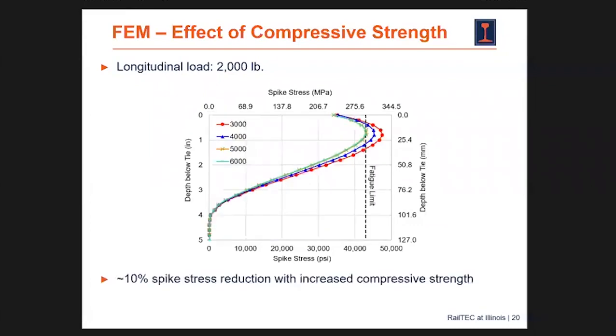Again, we're applying a 2,000-pound longitudinal load. And whenever we look at our values, originally we're above our fatigue limit. So we would expect failure to occur whenever we have only 3,000 pounds or 3,000 PSI material, composite tie strength, compressive strength. But as we get stronger, we end up going below that fatigue limit at this specific 2,000-pound load.